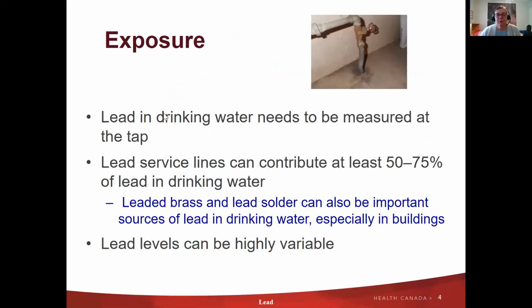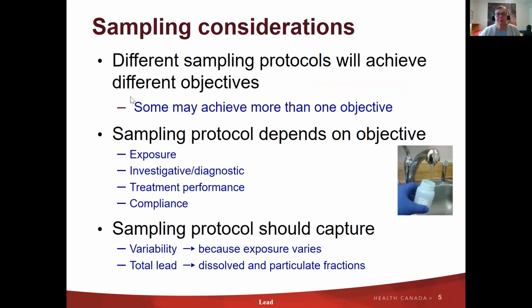In terms of exposure, lead in drinking water needs to be measured at the tap, and that's simply because the source of lead is not actually the treatment plant. It is really from materials that come into contact with water after it's left the treatment plant. In particular, lead service lines can contribute at least 50 to 75% of lead in the drinking water. As well, leaded brasses and lead solder can also be another important source of lead in drinking water, especially in buildings, and in particular larger buildings. And lead levels can be very highly variable.